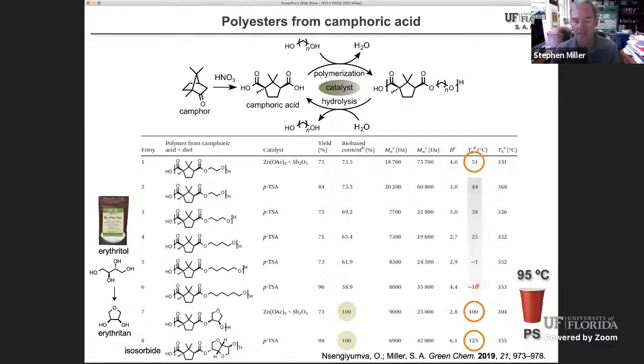Both of them can be incorporated, copolymerized with camphoric acid. And in that case, you have a more rigid diol that you're employing with 1 or 2 rings in it, and you get Tgs of around 100 or 125. So those are interesting from that standpoint because you get to really boost your glass transition temperature from a terpene and from a sugar as feedstocks.